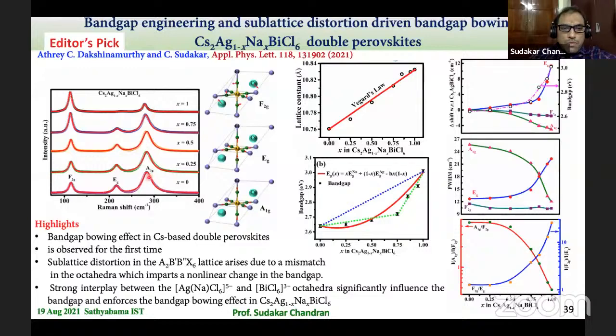these peaks, the shift in the peak positions and things all show how the octahedral structural features change. And you can see that around 60-70%, there is a sharp change, and that's the same region where you also find the band gap changes very sharply. And this implies that the sublattice distortion that we can manipulate by sodium substitution in this double perovskite is very important, and therefore it controls the band gap.